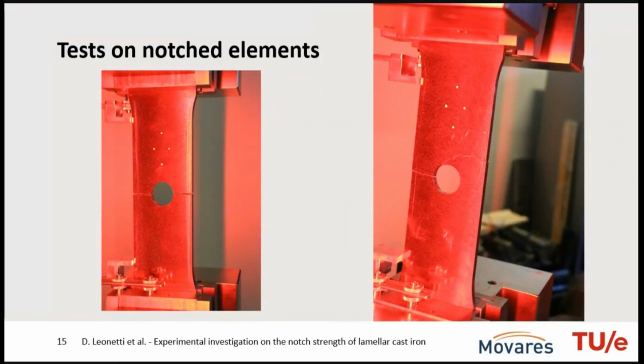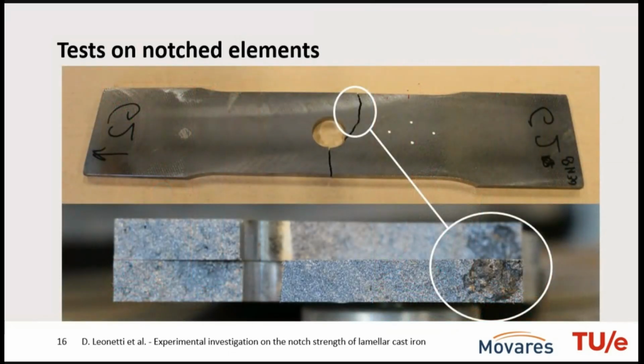So you can see here two typical tests. In this case, one that went well, where, although you don't see it very clearly, the fracture occurs, or at least the trigger point of fracture is at the root of the notch. Instead, for these other specimens, that is not clear here, but luckily I had another picture, you observe this crack path. Well, you can imagine the reaction when this occurred at first glance. But in fact, the reason was a shrinkage, another type of casting defect, close to the hole that induced this curved crack path due to the stress distribution. You can imagine the crack will follow to the hole, and then eventually the second ligament snapped.